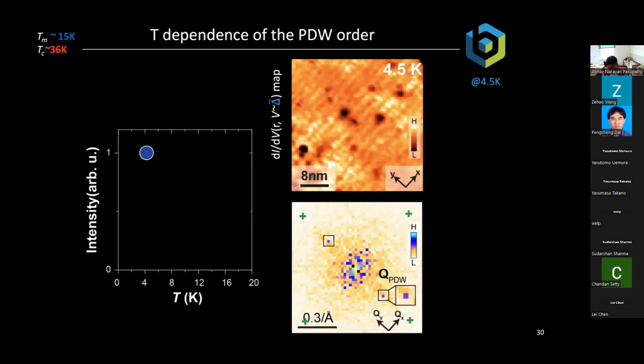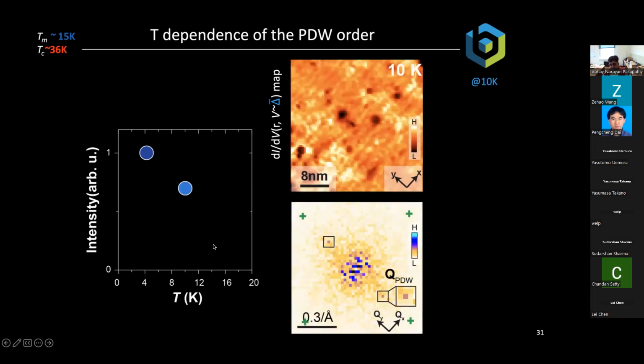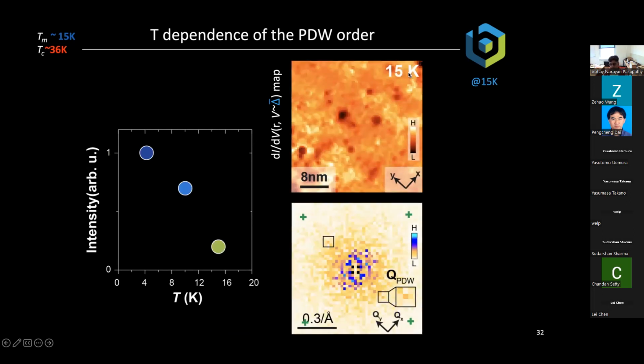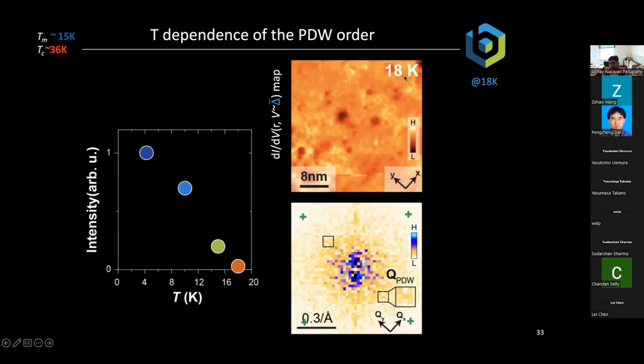And so in order to do this, we pick a region of the sample. We start at low temperature where we see these stripe modulations, and we raise the temperature and look at this phenomenon. And as we do that, so this is 10 Kelvin, 15, which is just close to the magnetic transition temperature, and 18, which is just above the magnetic transition temperature.